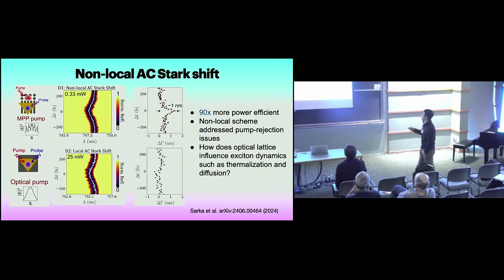One thing we notice is that in addition to the shift of the neutral exciton energy, there is also significant broadening when we pump the system with surface plasmon polaritons. So you see that there is broadening for this SPP pumped case, but no broadening for this conventional case. This is due to the lattice effect, right? Because we have a lattice, different regions have different amounts of shift. So if you average them out, you would broaden the bandwidth.